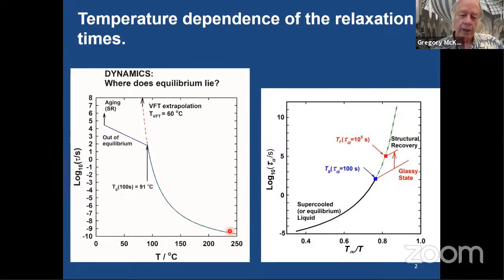And this is what Ken was talking about, whether you have three domains here or not. What we know is when we get to this relaxation time of about 100 seconds, you fall out of equilibrium when you're doing an experiment, because your experiment usually is taking less than 100 seconds, or it could be 10,000 seconds as we show here. But what we see is then something like the relaxation times then fall over onto some other line with a very different behavior. The question arises, what happens as I go towards equilibrium?